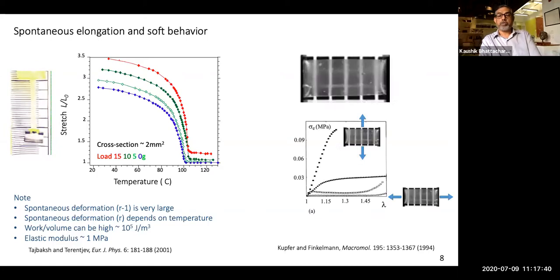The other aspect is one that you see here, is the soft behavior. If I take a piece of this rubber, which is prepared in a particular way, and pull in this direction, you find that the stress versus stretch behaves in this way. If you pull in a certain other direction, you find that you have the usual rubber-like elasticity, but transverse to it, you find very soft behavior. Here I describe the behavior with respect to temperature, but you can induce this phase transition using light, electric field, and other stimuli by preparing the material appropriately.